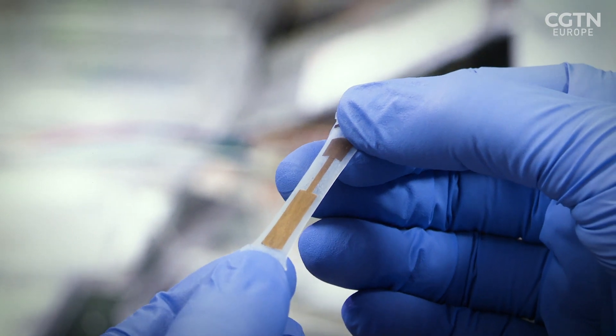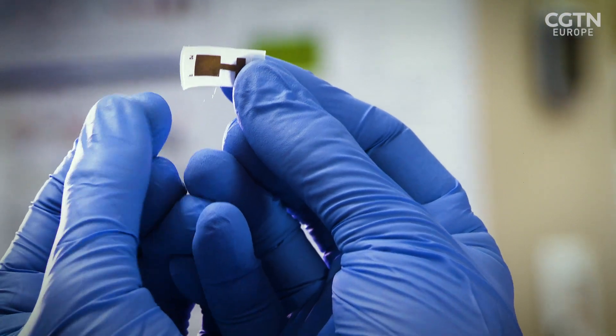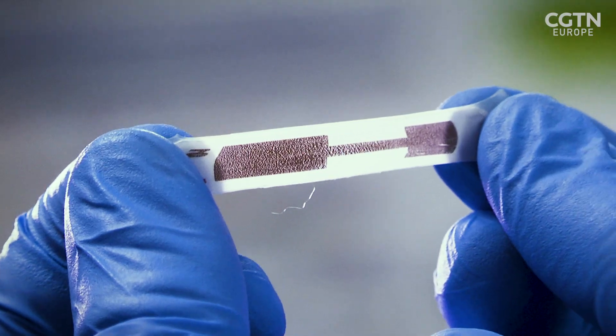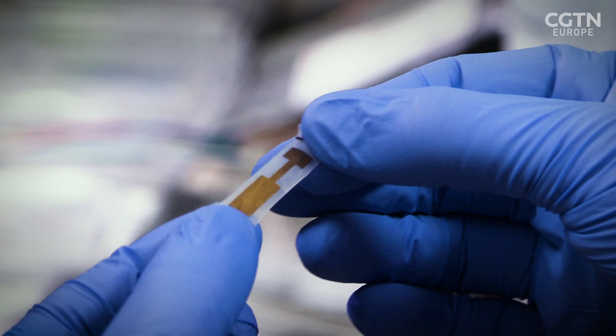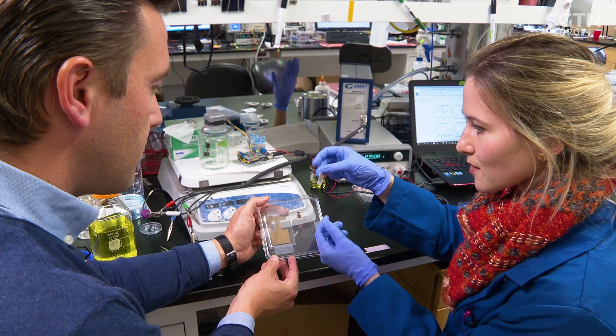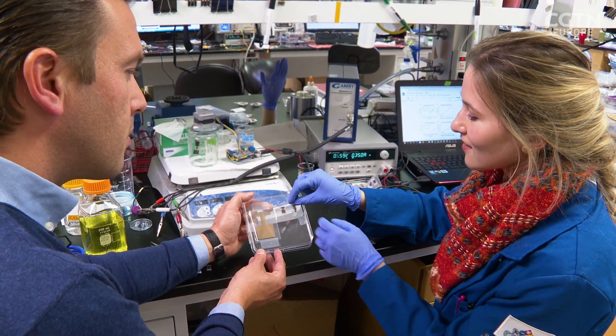Visually, you can see white spots and cracks in the gold — it used to be solid and opaque, but when stretched, a lighter color comes through because the gold physically separates. The first stretch really breaks the gold, creating a lot of fracturing in the film that exposes new surface area for picking up more signal, while also stabilizing the thin film to result in less noise. Starting at about 10 square centimeters, after shrinking it gets much smaller, and by the time it's transferred to the stretchy substrate it has shrunk by more than 95% of its original size.